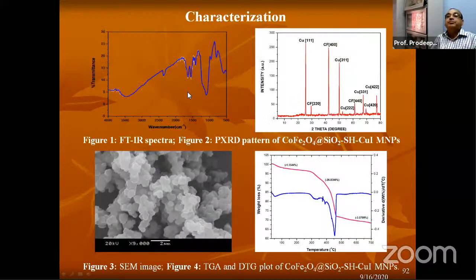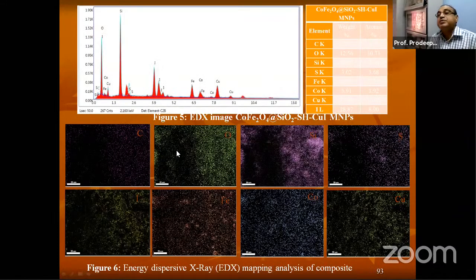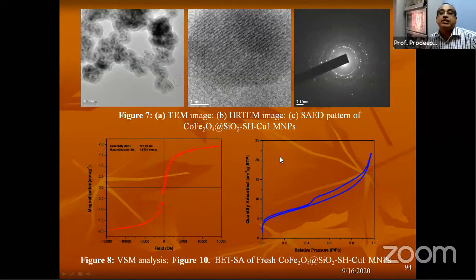So these are the different XRD pattern and IR, all these things, SEM. Then this is a mapping analysis. It shows a uniform distribution of the cuprous iodide and other materials on the surface of the catalyst. So different elements, carbon, oxygen, silicon, sulfur, these are the distributions. Also iodine and copper, cobalt, iron. You see here, copper is about 17 weight% and iodine 28 weight%. And this is the TEM image, then the HRTEM. So we will not discuss much about this.